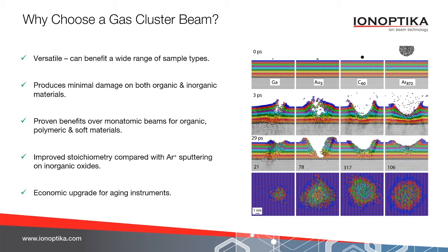So a gallium ion beam, for example, but it also applies to something like argon, would penetrate very deep within the sample and actually doesn't produce that many sputtered ions. So it's not a very efficient sputtering beam. It also damages the sample very deep within the surface. So many layers beneath the surface, the bonds have broken. And so if you try to analyze that material, it will be different to the pristine material.